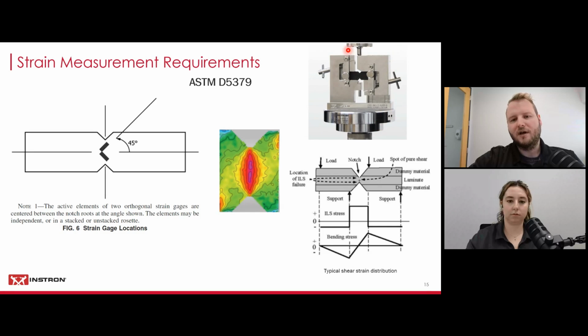And you can see the fixture with the specimen in here. It would be loaded from the top. It's sitting on a compression platen, and then this anvil here would come down and initiate the load into the specimen. So for this one, really, there's only strain gauges you can use. The other option you could think about would be a full field DIC, which, this is obviously very localized with the strain gauges, and the DIC then gives you the full field, and you can then later on go and apply the strain gauges in the areas that are most interesting to you.